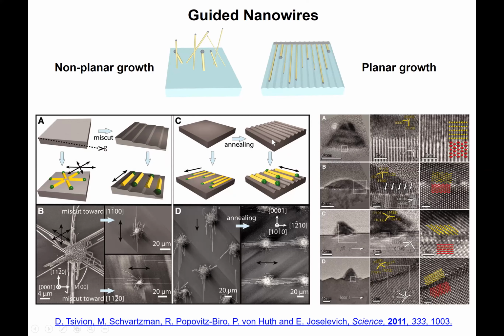If the surface is faceted, it can be spontaneously faceted with nanosteps or nanogrooves, then they grow along these features that are larger than the lattice parameter, and this is called graphoepitaxy. And the combination of epitaxy and graphoepitaxy allows us not only to control the direction of the growth of the nanowires, but also the crystallographic orientation.